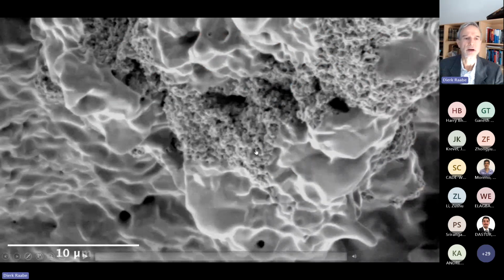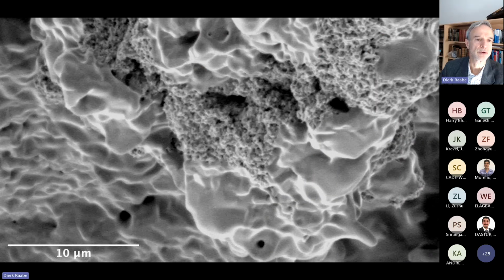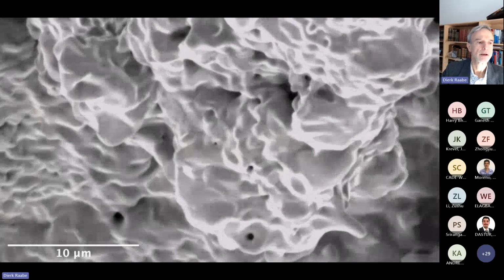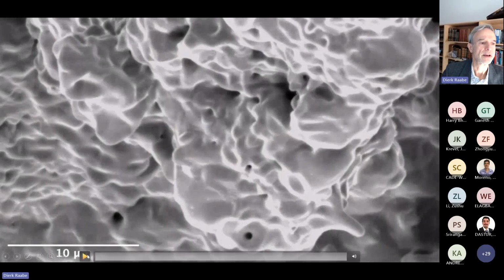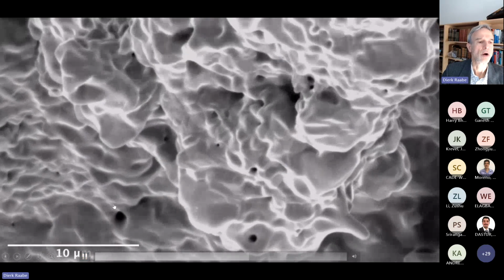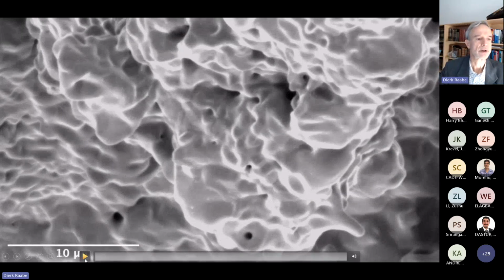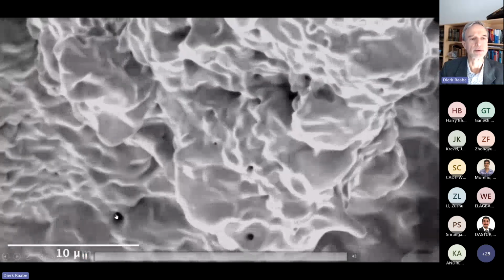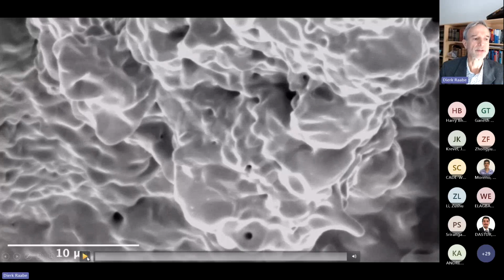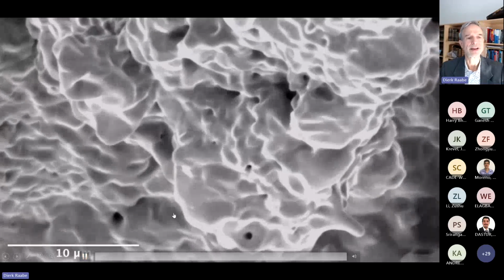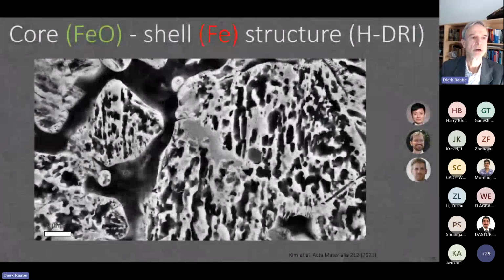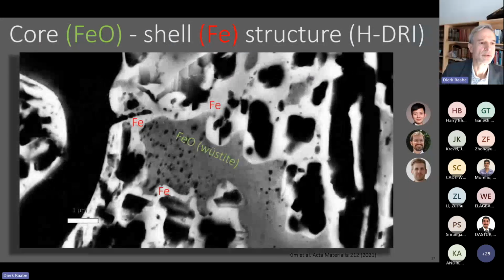Here you can see a very nice in situ SEM experiment that was done by my colleague, Professor Mark Willinger, in an environmental SEM microscope. And you can see when I play this again, how the single crystalline wüstite that we had exposed here to pure hydrogen in the microscope is overgrown by this dense layer of pure iron. So that is creating a core shell type of structure. And when we cut that through, then we see when we look at it from the side, how you have in the interior this very porous iron oxide sponge.